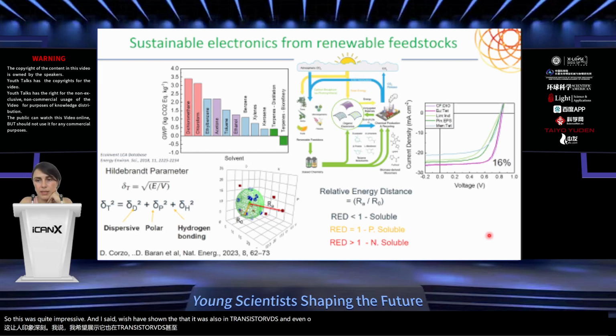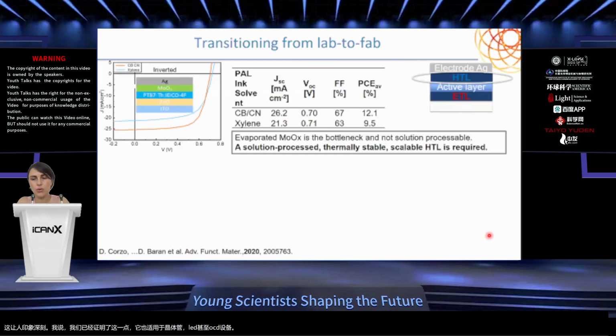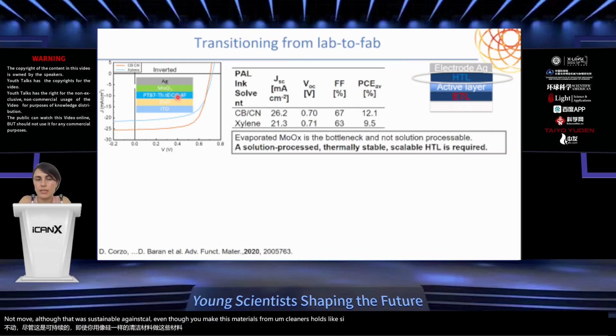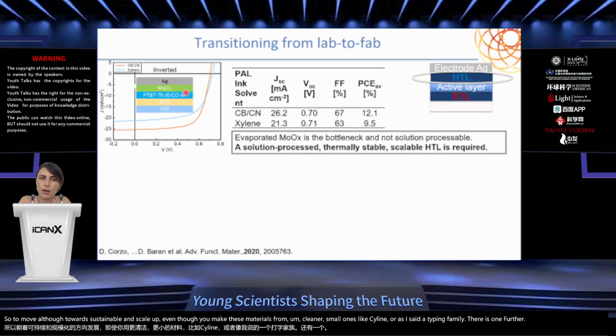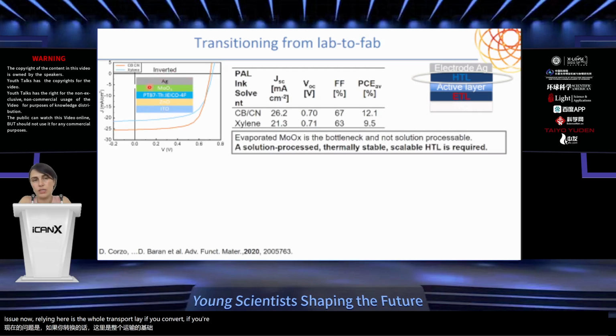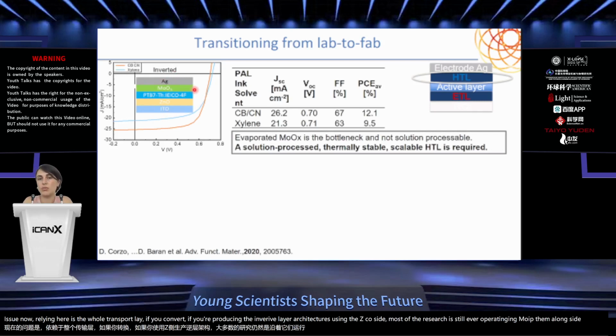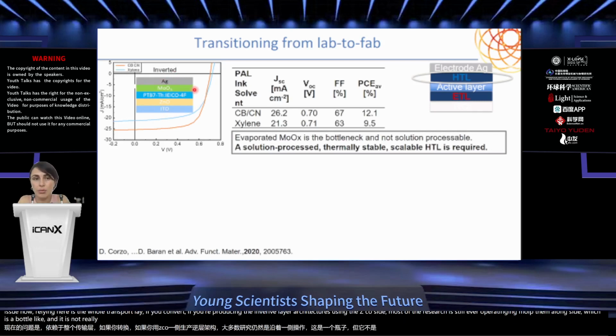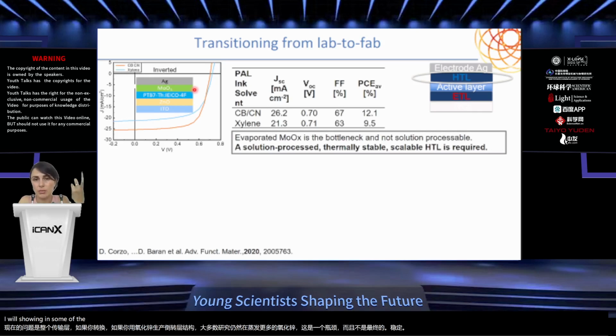So this was quite impressive, and as I said, we have shown that it works also in transistors, LEDs, and even OECT devices. So to move on though, towards sustainability and scale up, even though you make these materials from cleaner solvents like xylene or, as I said, the terpene family, there is one further issue now, which is the whole transport layer. If you're producing the inverted layer architectures using zinc oxide, most of the research is still evaporating molybdenum oxide, which is a bottleneck, and it is not really thermally stable, which I will show you in some of the outdoor stability data.